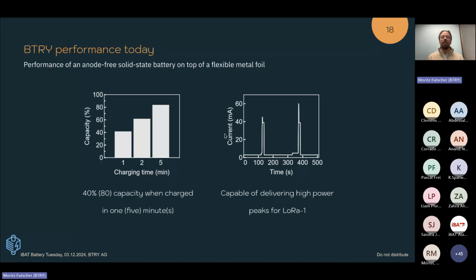We also showed that we can get very high power peaks out of these cells. So here on the right, one customer which we're talking to, he is using cells to send signals using LoRaWAN. LoRaWAN is a sending protocol which usually needs power peaks of 60 milliamps. So often there's a capacitor used for that in combination with a battery. And here we demonstrated that with a cell, which had just a bit less than 2 milliamp hours, we could still deliver this high peak current of up to 60 milliamp, which would make it feasible to send signals via LoRaWAN.